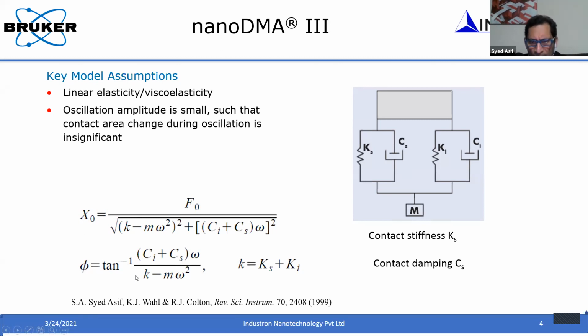So the main focus is how we can measure the contact stiffness when you do this experiment, because the most important measurement in nanoindentation is the stiffness. Okay, as long as you measure the stiffness correctly, and if you have a good area calibration, you will end up with a nice measurement. So when you measure this stiffness by this force modulation technique, that gives you a better sense of measuring the modulus and hardness of the material.